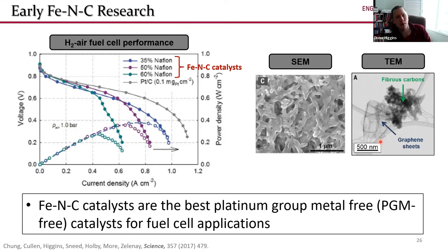They've actually been around in the fuel cell literature for a little while. And actually iron nitrogen carbon catalysts are currently the best non-platinum based catalysts for fuel cell applications, particularly the oxygen reduction that occurs at the cathode. There is no other non-platinum based catalyst, or I should say non-platinum group metal catalyst, that performs better than these iron nitrogen carbon catalysts that are prepared by relatively simple and relatively cheap processes.